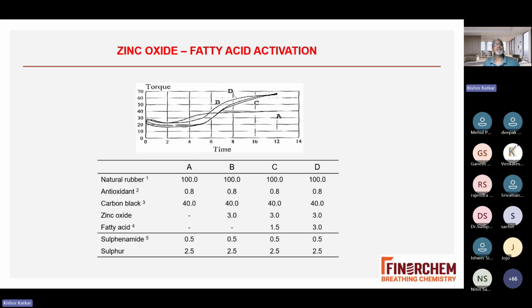Now, very important, zinc oxide and fatty acid activation. Here what I have proved is that if you don't use the proper optimum dosage of zinc oxide and fatty acid, you will not get a proper cure. Graphs are not very clear, but you can see here there are 4 compounds A, B, C, D. In A, the natural rubber, antioxidant, and carbon black are common. In the first case, the compounder has forgotten zinc oxide and fatty acid. Now you can see there is no curing, it is going flat.